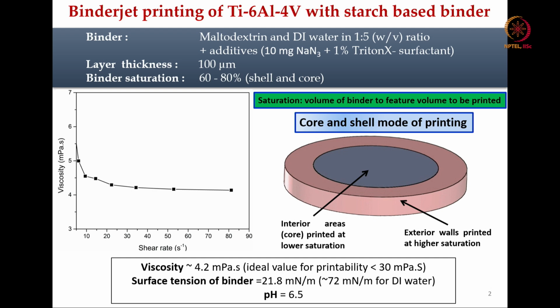What is core and what is shell mode of printing, that I am showing here, and then I am going to show another scientific case study in the subsequent lectures, where I will show that this core shell mode of printing essentially is not advantageous for ceramics, and it leads to inhomogeneous microstructure and properties, but for metals it has not been that challenging, and we have used some binder saturation 60 to 80%.